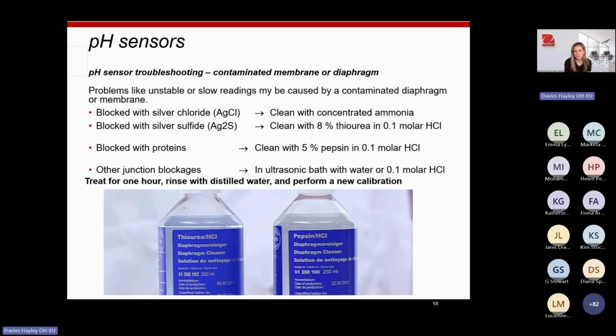If you've got samples that are high in proteins, then 5% pepsin works in 0.1 molar HCl. And if you've got something that's really sticking in the junction, and you can't clear the blockages of your junctions, what we suggest is popping your electrode in your electrode cleaning solution, whether it be the pepsin or the thiourea, into a beaker, and then put that beaker into an ultrasonic bath, and let the ultrasonic bath do its work. That should agitate anything that's blocking the junction, and that should release that and hopefully get that clear.